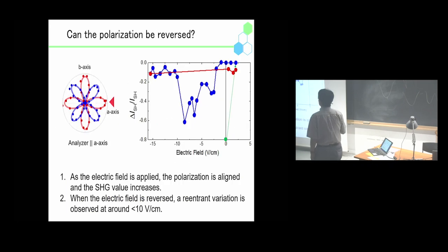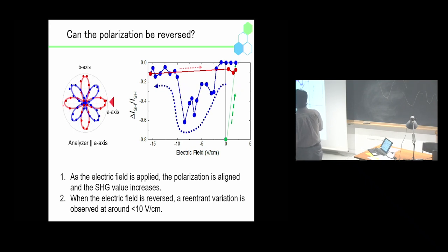Okay, so I will show you the results. This is the electric field dependence of the relative change of the SHG. This is the D11 component, the strongest SHG point. Let's start from here. As the electric field is applied, the polarization in the crystal is aligned, and the SHG value increases from here to the blue circles. When the electric field is reversed, a reentrant variation is observed at around 10 volts per centimeter. And finally, with decreasing electric field, the change of the SHG is kept from here to here. So this electric field dependence of the SHG is a little bit complicated, but the scenario is quite simple.